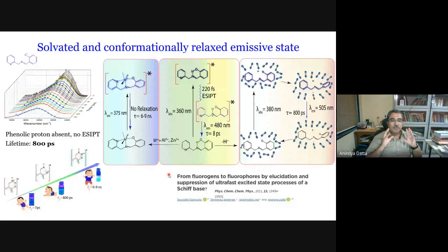And the lifetime of this fluorescent excited state of the anion is about 800 picoseconds. Upon performing experiments on a faster time scale, we saw signatures of solvation and most likely conformational relaxation. So it appears that for the anion, solvation and conformational relaxation prepare the emissive excited state, which has a characteristic lifetime of 800 picoseconds.